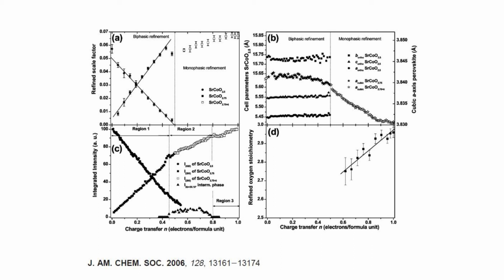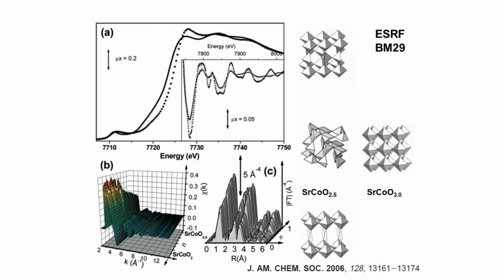How is the charge balanced? Because we must have a neutral solid at each step. Of course, the trick is that the transition metal, cobalt in this case, but iron will do the same job, will change oxidation state during this transformation. Neutron diffraction, but also whatever diffraction, will not tell you any information about the oxidation state of cobalt, but X-ray absorption spectroscopy will. And so we have repeated the same experiment at the synchrotron in X-ray absorption spectroscopy.